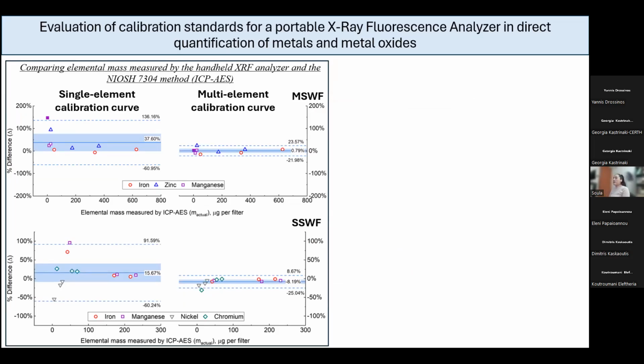So this is what I tested. These are some Bland-Altman plots that show the percent difference of a handheld XRF analyzer compared to the established NIOSH method that uses ICP-AES for the detection of metals. In the first column, I have the quantification when single element calibration curves were used, while in the second column I have the quantification when multi-element calibration curves are used. And as was expected, in the second case, we get way better results, way better agreement between the two analytical techniques, just because the interferences are not a problem anymore when we have multi-element calibration curves.